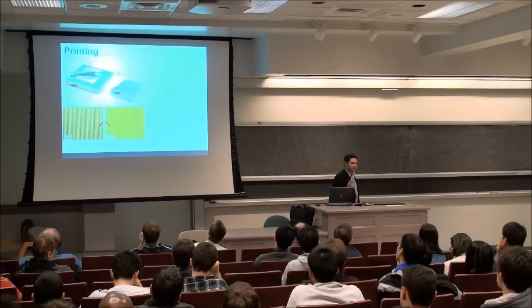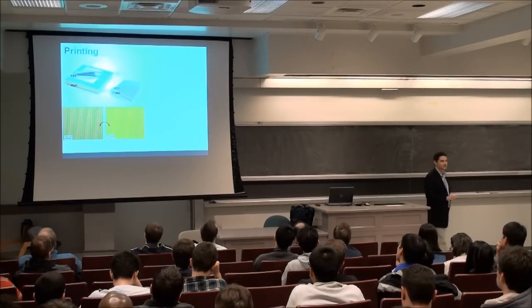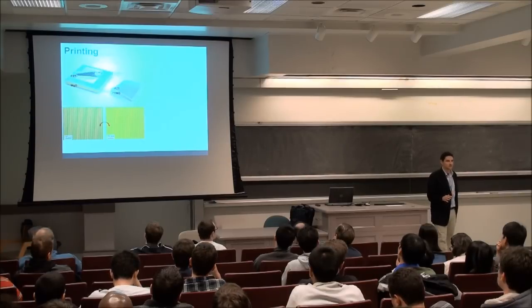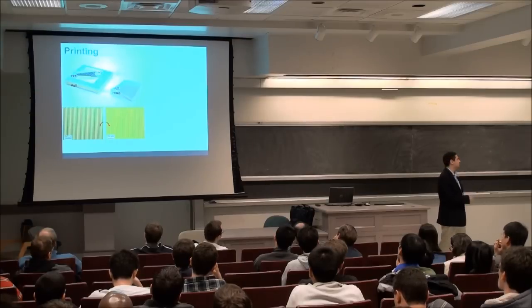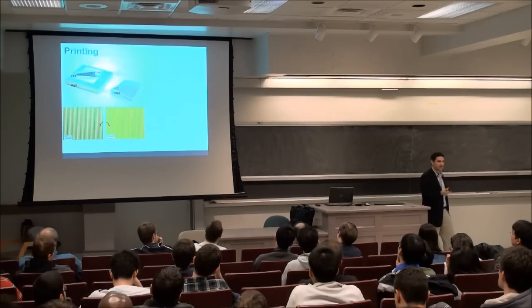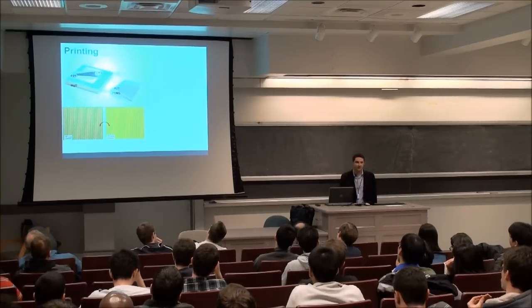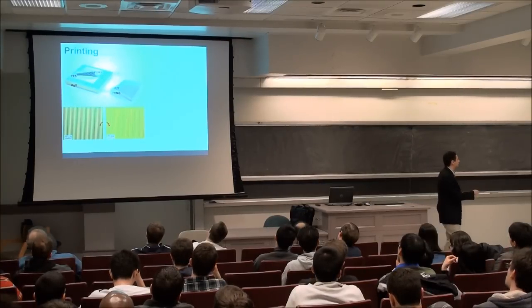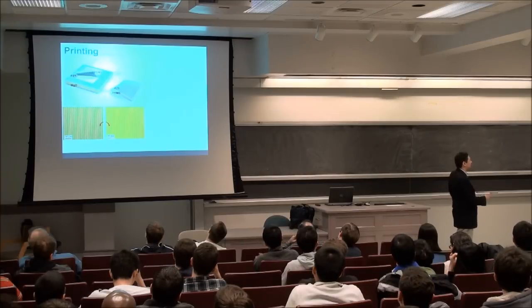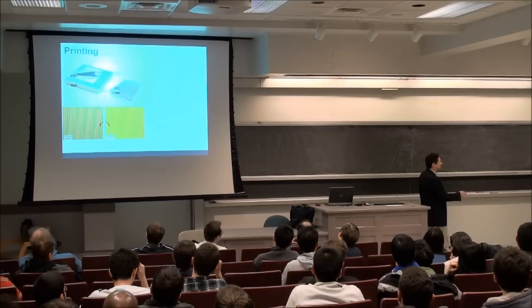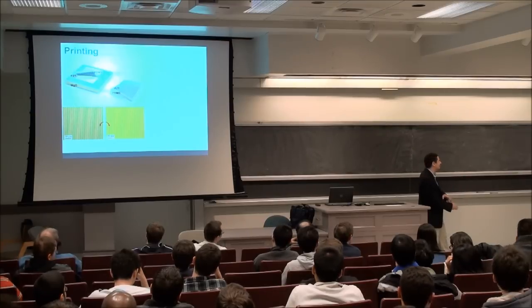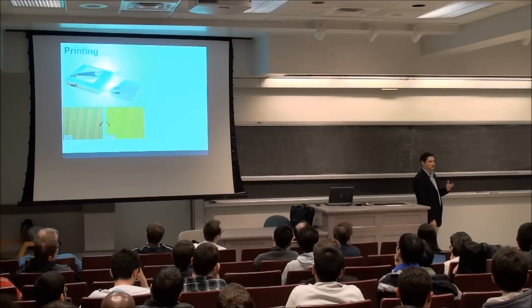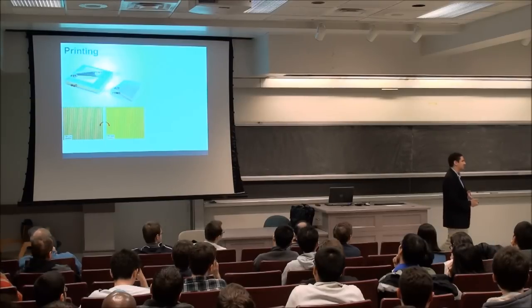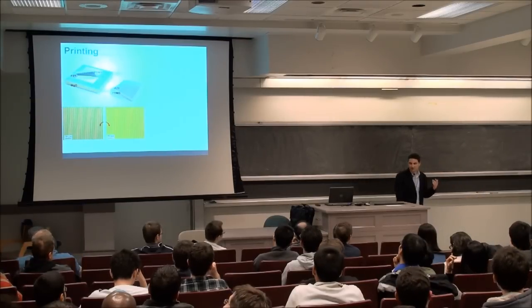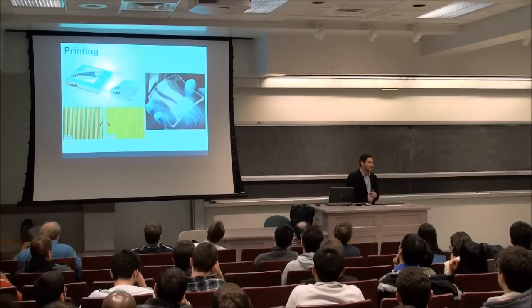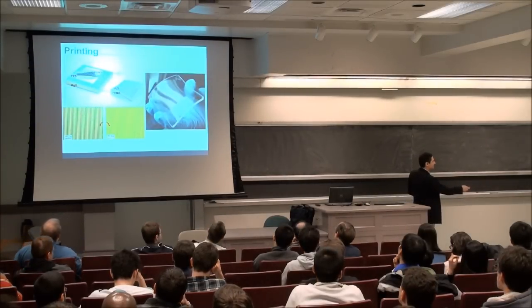So what we did in our case is we started with a thin film, because there have been decades of research on growing nice crystalline stoichiometric thin films of PZT, and then we carve it up into nanoscale structures that you can see here. The magnesium oxide is the closest lattice match with PZT that we can find. If you take this wafer and dissolve it, which is obviously inspired by John Rogers, except in our case we're dissolving the entire wafer, we can print this, just like you print newspaper ink on Silly Putty, onto this silicone platform, which is of course a biocompatible platform, and silicone is used in cosmetic implants, right? And just like you do with silicon, you can do this over large areas. This is the outline of the wafer with high yield.